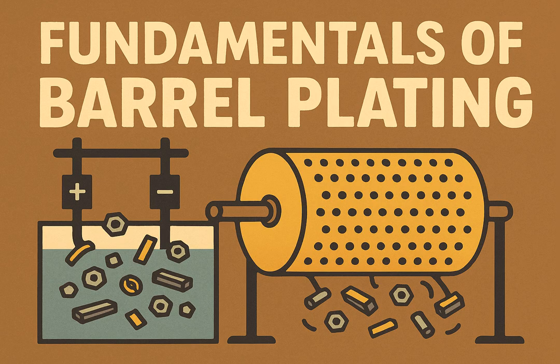Yeah. Big ones. Significant ones, yes. The major disadvantage is that any areas that are cut, stamped, or formed during fabrication will be left unplated. Ah, so the edges are bare metal. Exactly. This means edges, holes, and cutaway sections have no plating protection. This drastically reduces the corrosion resistance of the final part, making pre-plating unsuitable for components exposed to harsh or corrosive environments. If the part design involves extensive cutting or shaping, a large portion of the final surface could be unprotected. So great for cost, potentially terrible for corrosion resistance at the edges. That's the trade-off. The appearance can also be less uniform compared to post-plating, and parts that require heat treatment after fabrication usually need post-plating because the high temperatures can affect the pre-plated layer's integrity.